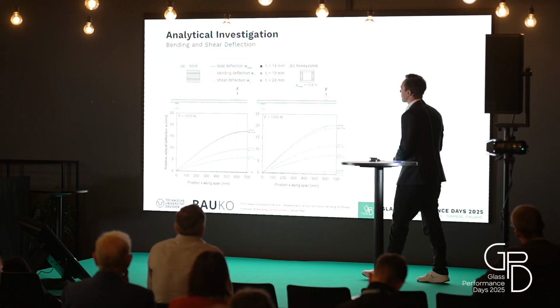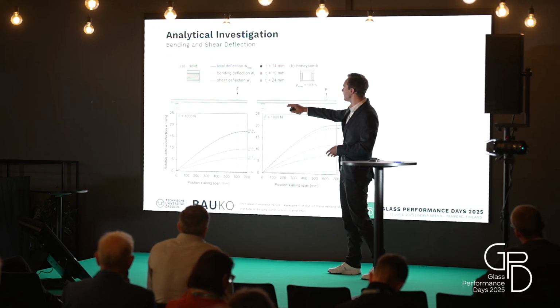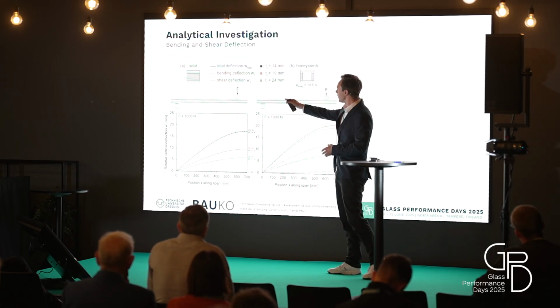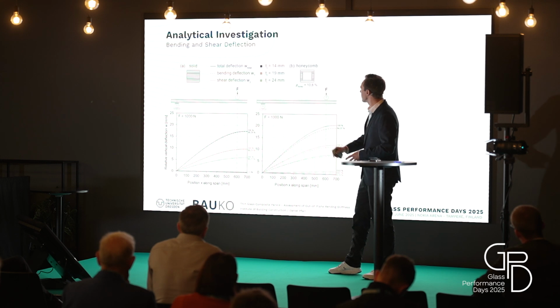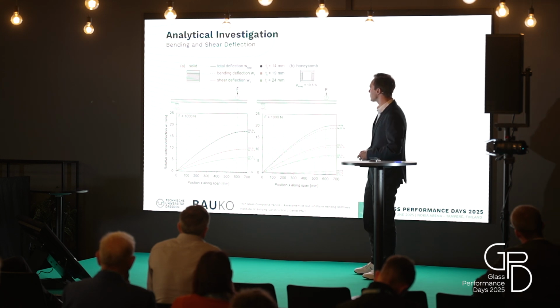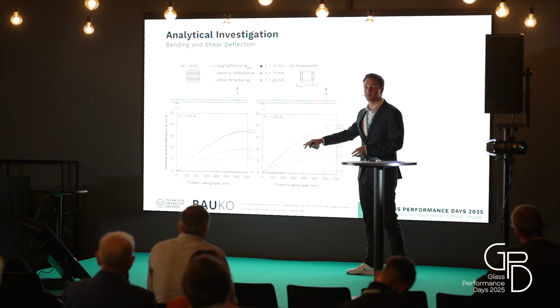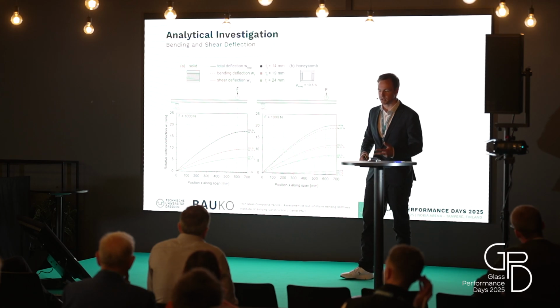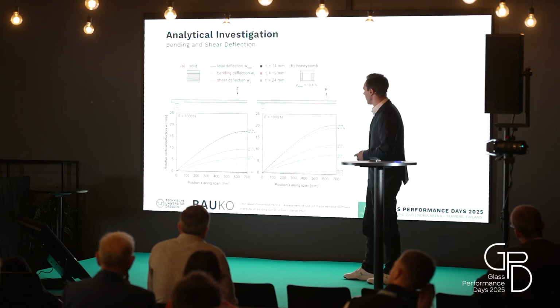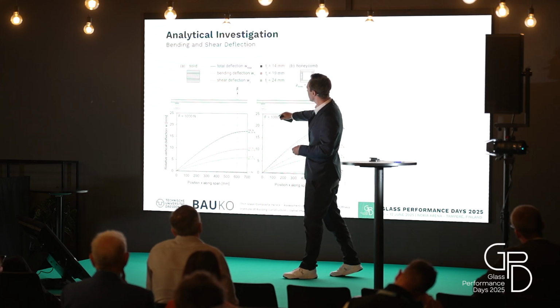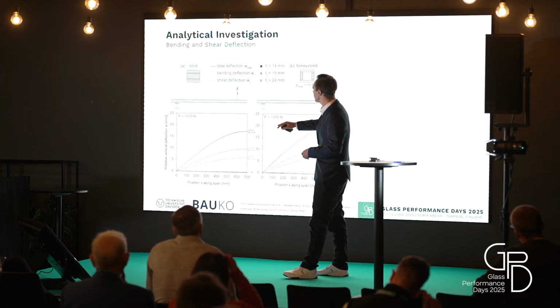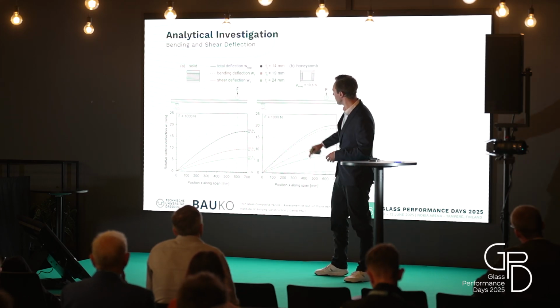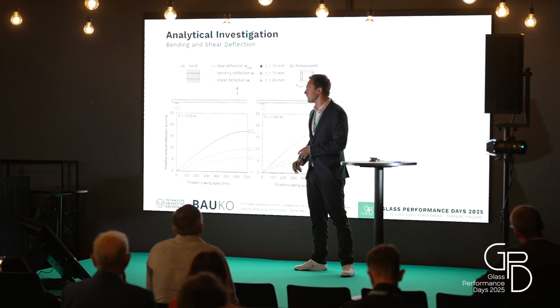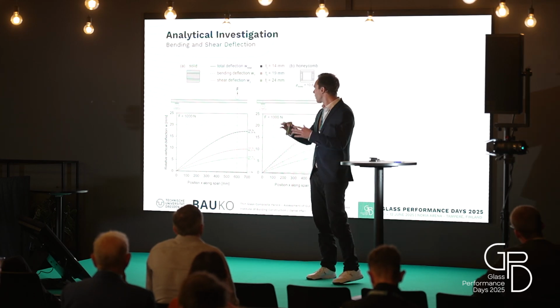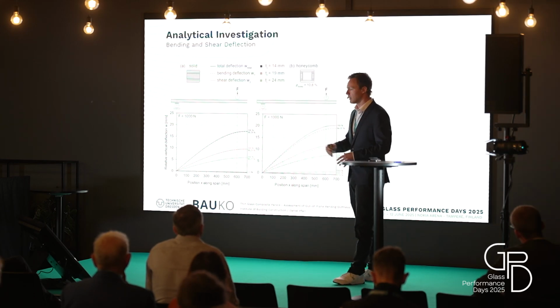So in that graph we have represented our 4-point bending test, only the half of it. On the left side is the solid assumption, on the right-hand side the honeycomb assumption, and then we have our 3 colors representing the 3 different thicknesses which we have investigated, and then we see some dotted lines and some dashed lines. The dashed line is the bending deflection, the dotted line, which is here almost 0, is the shear deflection, and then the total deflection is a solid line.